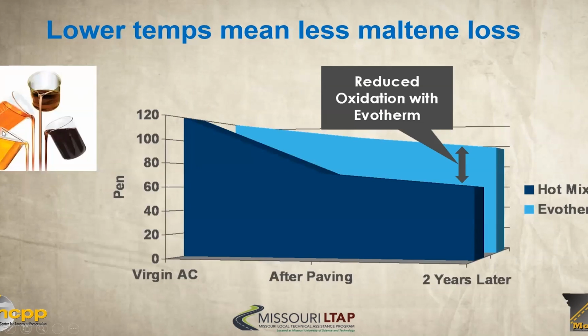So just as we talked about in Module 3, the maltenes or the light ends, those are the four components that make up the maltenes versus the asphaltenes in the asphalt binder. This is also helping us with warm mix because less of these maltene fractions oxidize, volatilize, and leave the asphalt under the hotter conditions or cooler conditions. So in this instance, this again with NCAT, you saw this reduced oxidation with the warm mix technology here. And so that equates to obviously a longer binder life after 2 years.